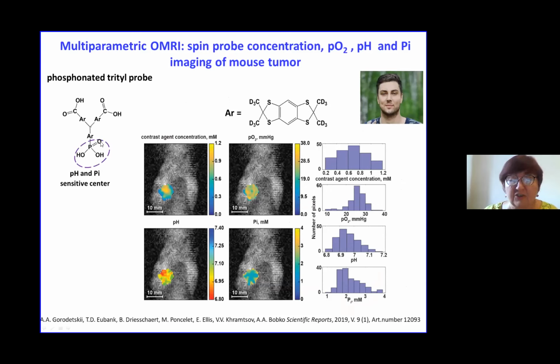They synthesize such a trityl radical with this phosphonate group. And this trityl is multifunctional. First of all, one can measure oxygen by the line width, one can measure pH because this group is sensitive to pH, and one can measure concentration of phosphate. And concentration of phosphate, during the last years, it was admitted that it plays a significant role in the cancer tumor. So, and here you see these images.